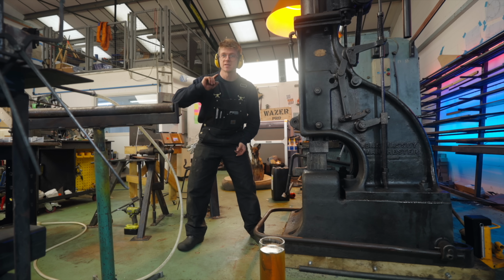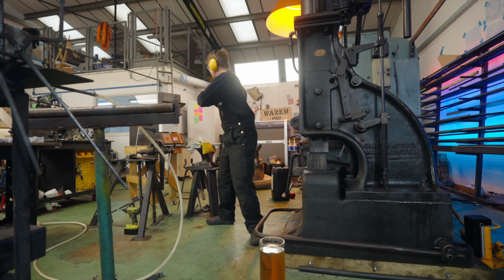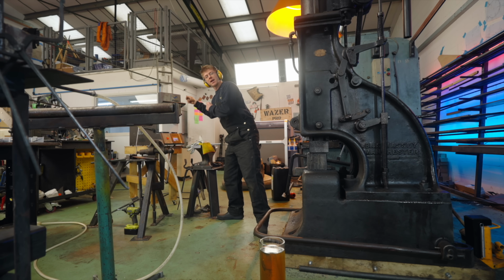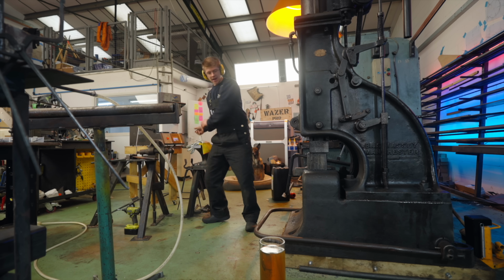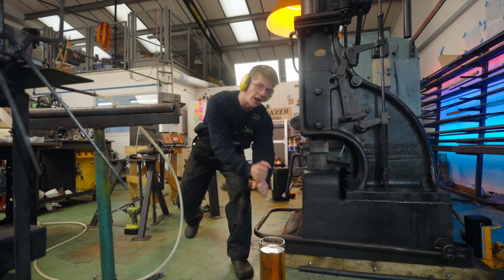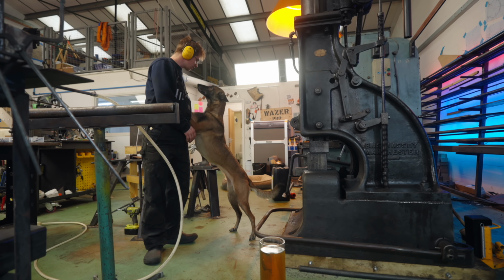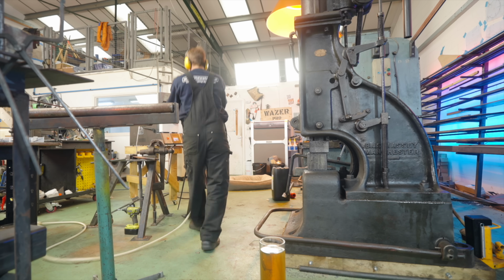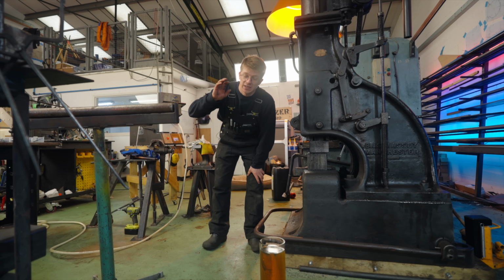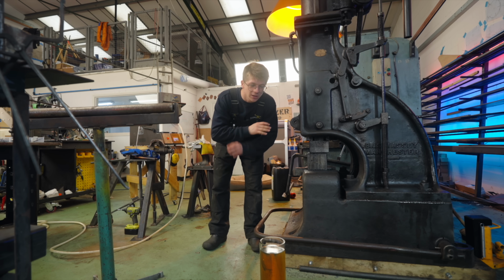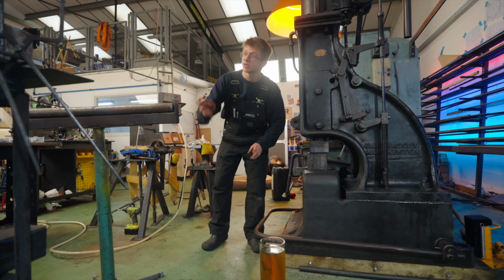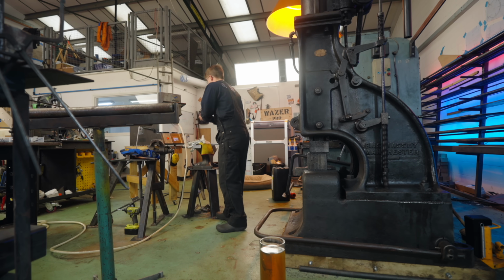I'm going to preheat to about 700 Celsius in the gas forge, then take it to the heat-treating oven to get it up to 850 Celsius. We'll come out of here, boom, boom, boom, boom, boom, quench. What you reckon? Think it's going to work? Okay, preheating. I'm doing the preheat so that we get as little time at temperature as possible. I want it to heat up as quick as possible, and the gas forge is going to heat it up quicker. Come on, Betty.